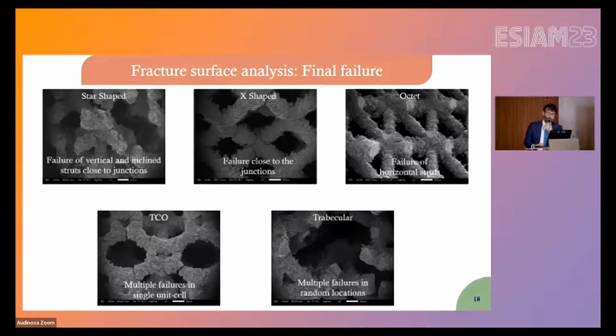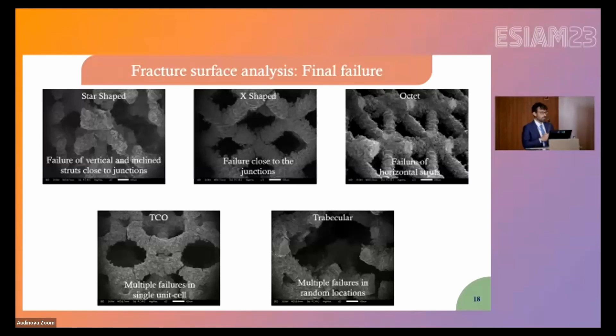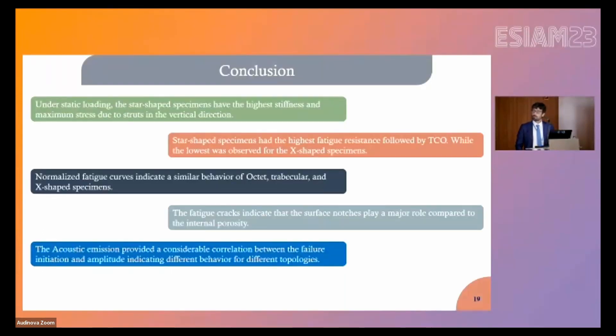Finite element analysis of these lattices shows that, even though the remote applied load is compressive, the horizontal struts in the octet truss are subjected to tensile loads. Since tensile fatigue is much more detrimental than compressive fatigue, this explains the poor fatigue performance of the octet truss. I now come to the main conclusions listed on screen. I wish you a nice lunch and the continuation of the conference — thank you very much for your attention.